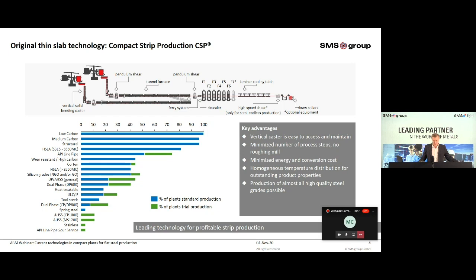casting machines, a pendulum shear to cut the strand into slabs, a tunnel furnace to heat and to homogenize the slab, and as a buffer for the compact hot rolling mill. The mill has typically 6 to 7 rolling stands, followed by a laminar cooling table to cool down the strip and to adjust the material properties of the product. At the end, the strip is coiled at the downcoilers.